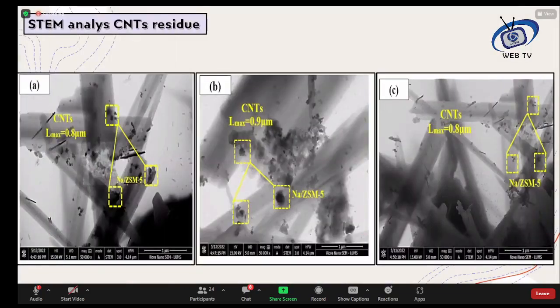Then we performed STEM analysis of the residue to check further whether these are carbon nanotubes, and if so, whether they are single-walled or multi-walled carbon nanotubes. Image A was the residue produced with HDPE, image B was produced with PP, and image C was produced with a mixture of the two. We can see that in image C the tube structure is much better compared to A and B, and the diameter is also in a controlled range. The amorphous or impurity content of the product is also low compared to the first two images.